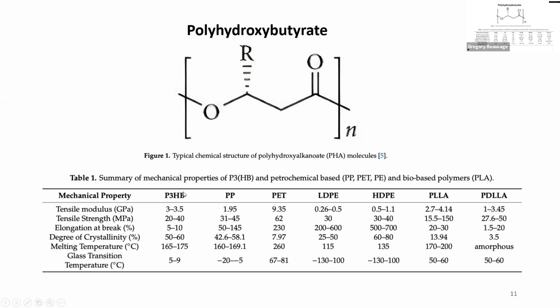I think they don't give the other copolymers here, which have different glass transition temperatures. Then the melting is okay. It's even higher than the polyolefins, like 165. The PLA though, let's see. PLA has a glass transition at 50 to 60, so it's normally glassy when you have it. Well, let's see, they give a degree of crystallinity. So it's 10% crystalline or 3%. These are the two different stereochemical, left and right stereoisomers. They have the same glass transition, but one's amorphous and one's slightly crystalline, 10%.